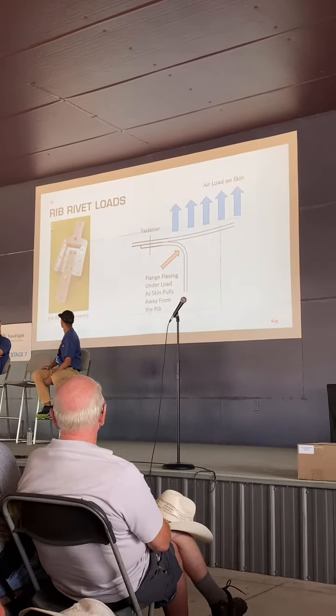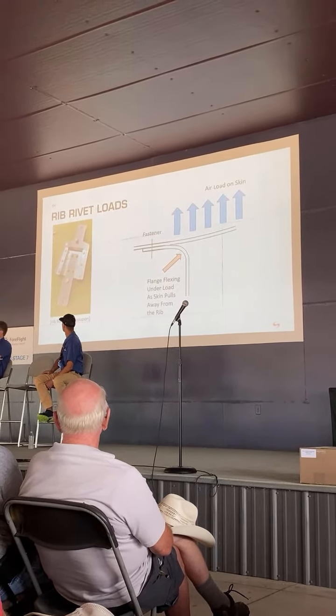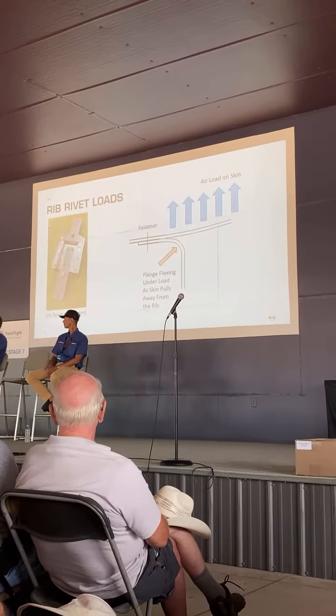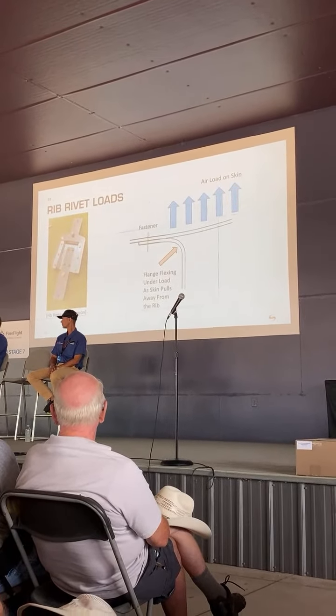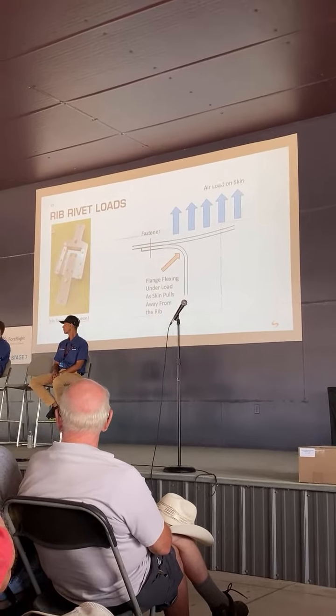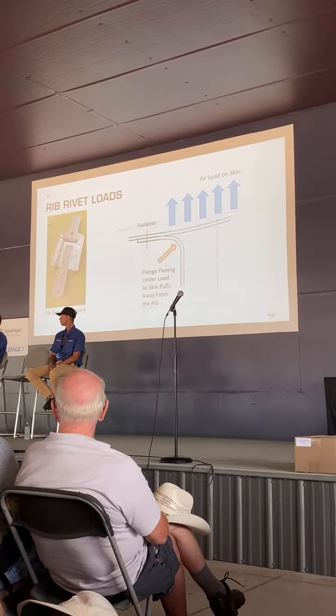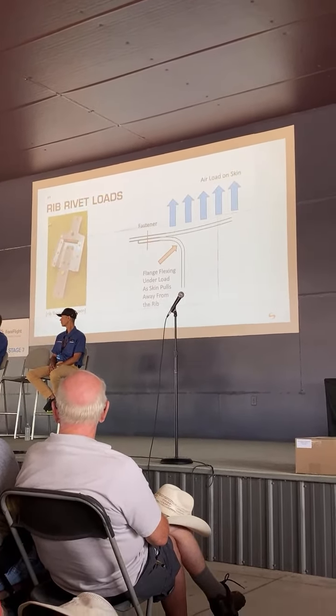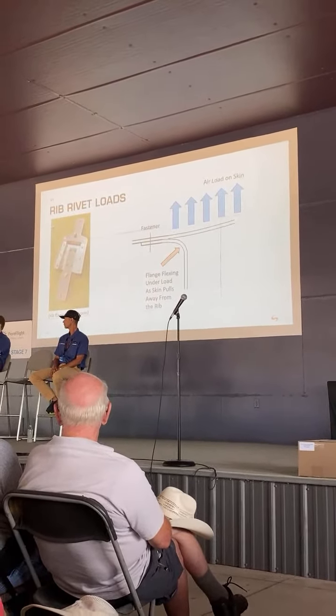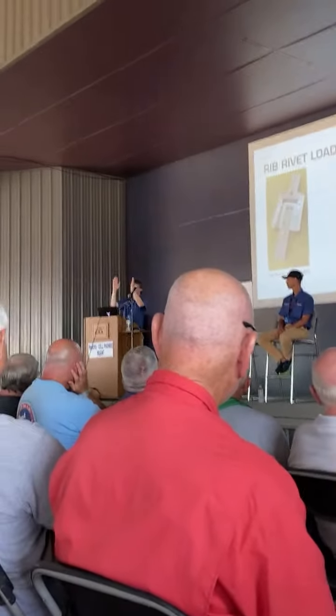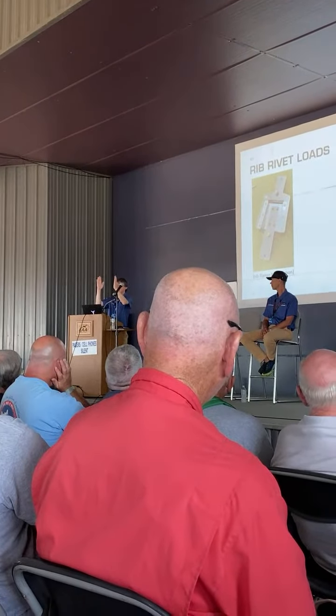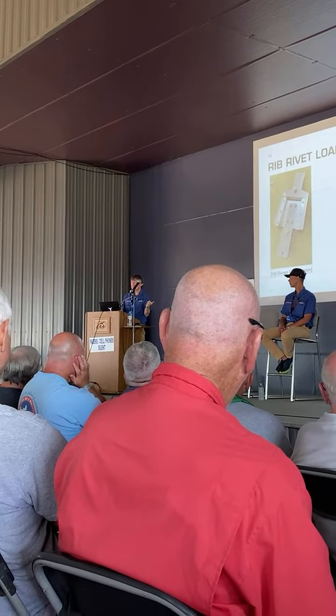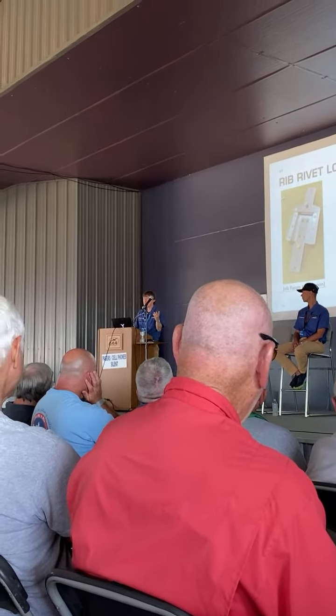The load is applied in this direction, and this has an angle on the sides of it. So the sides of the test coupon are angled in, and it does two things. Depending on the angle, if you had the test oriented this direction, it would be in pure tension, and this direction would be pure shear. So we can go into the finite element analysis model and know the ratio of shear to tension and set the correct angle. For the worst case, we take the worst case shear rivet and the worst case tension. We apply both in this test.